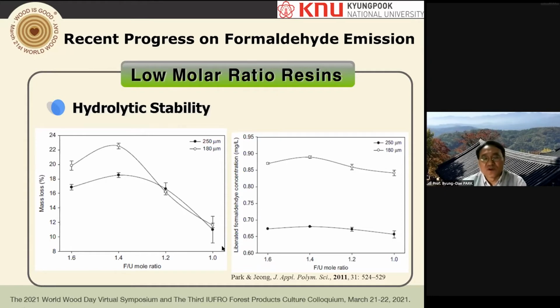Surprisingly, low molar ratio has much less mass loss. That means it is much more resistant to hydrolysis, which is very contrasting to the one we know. And the formaldehyde concentration shows a similar trend. That means the low molar ratio is a little bit more resistant to hydrolysis.